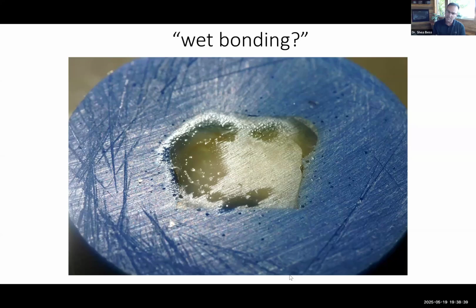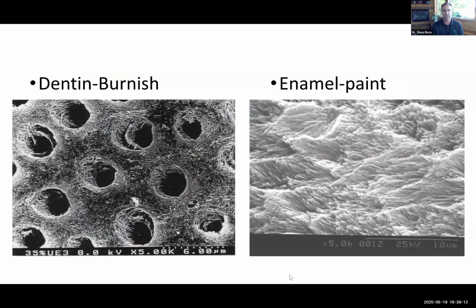Now, clinically speaking, that can be difficult to achieve. One of the best ways to achieve it is a good blast of air with your air water syringe to blow the water off the top, but don't sit there and continue to blow. If you keep blowing, you're going to over dry your dentin. And when you do that, you cause all of those collagen fibrils to collapse, and then you don't get as high of a bond strength. So really think about that right before you place your adhesive: completely saturated, no standing water on the top.